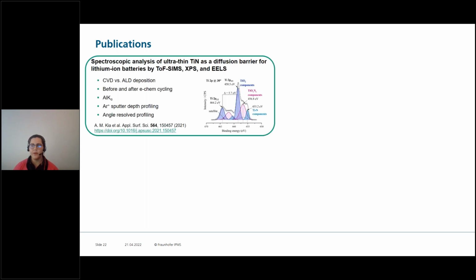So I want to show you today some examples of publications. We already published last year a paper entitled Spectroscopic Analysis of Ultra-Thin Titanium Nitride as a Diffusion Barrier for Lithium-Ion Batteries using TOF-SIMS, XPS, and EELS. What we did in this paper is that we deposited titanium nitride using 2 different deposition techniques, CVD and ALD, and we looked at the effects on this material before and after electrochemical cycling.